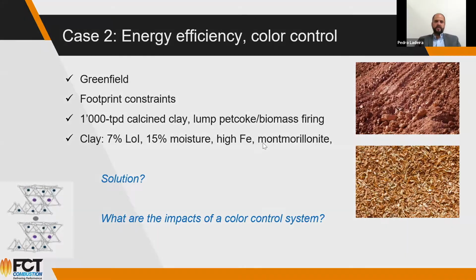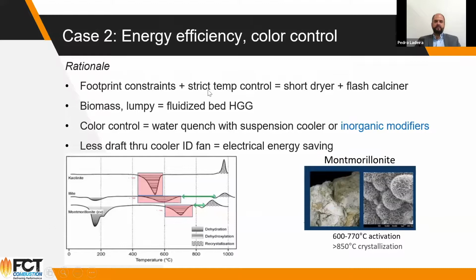So what does it mean? If you have a footprint constraint and a strict temperature control, you need a short dryer, you need a flash calciner. You want to use biomass, or you want lumpy petcoke, so you're going to go for fluidized bed, hot gas generator. If you want to have color control, you can use water quench with suspension cooler, or even inorganic modifier, which is a special feature from FCT. We can talk about this later.